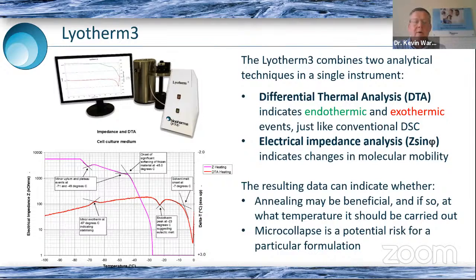Now, freeze drying microscopy, we tend to say that it gives us almost everything we need to know about almost all formulations, but there are a certain percentage of formulations which have much more complex behavior, and several examples where the active ingredient is accompanied by a number of different ingredients in the formulation, and therefore what you see under the microscope might give you a good indication of the temperature at which the material will physically lose structure and have visible defects after freeze drying, but it might not necessarily tell you everything you need to know. And this is where our impedance analysis comes in.